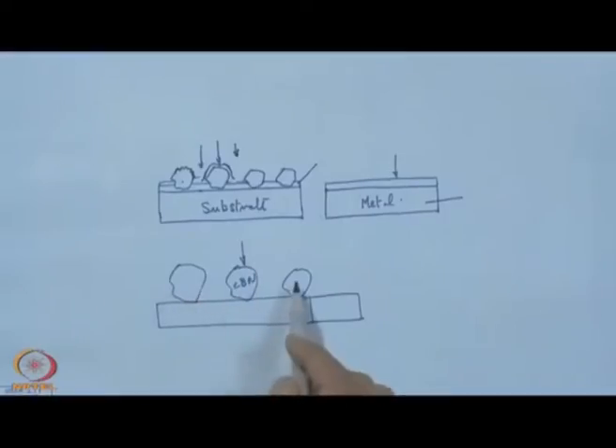So, that one layer can keep the same grinding behavior starting from the very beginning to the end, and this is not just a requirement for grit used in composite wheels, where resharpening of the grit is possible, but in this case with one layer configuration, resharpening of the grit is just not that easy, and this single layer configuration will keep on providing grinding results which are more or less uniform throughout the grinding span.